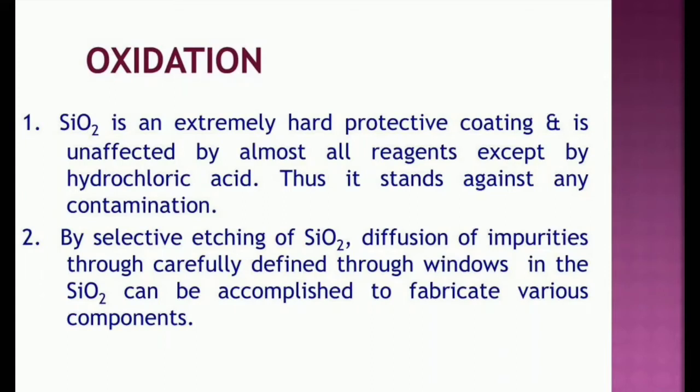The silicon wafers are stacked up in quartz boats, then inserted into the quartz furnace. The silicon wafers are raised to a high temperature in the range of 950 to 1150 degrees Celsius. At the same time, they are exposed to a gas containing O2 or H2O or both. In the chemical reaction, silicon reacts with water and produces silicon dioxide, and the hydrogen gas goes away. The oxidation process is called thermal oxidation because of the high temperature used to grow the oxide layer.